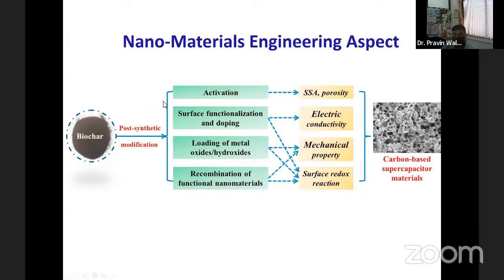And what is the requirement of our electrode material is that we need to have a good surface area of that material. If your surface area is large, then more sites will be available to adsorb the ions, right? And therefore, the EDLC layer formation will be higher. More ions will get accommodated on the larger surface area. And that's the reason we require more specific area, and we need a higher porosity.